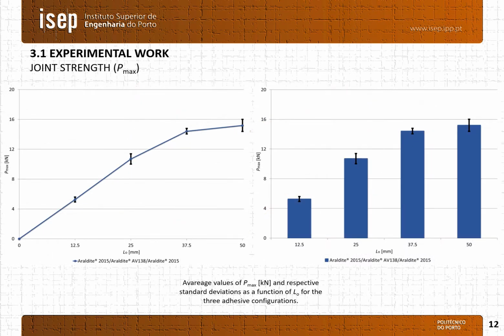In slide 12 is presented the evolution of the average Pmax as a function of the overlap length. It is possible to observe a remarkable Pmax increase for overlap lengths of 12.5, 25, and 37.5 mm, and a small increase for 50 mm. Also, the standard deviation values are small, which indicates very consistent results.